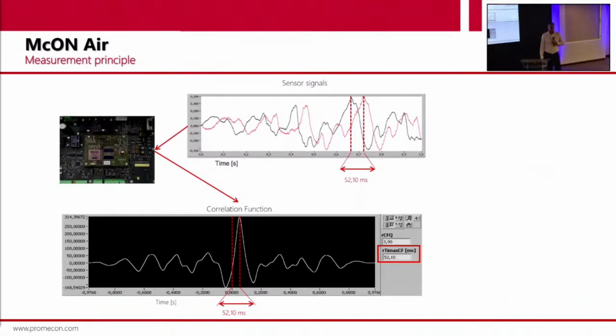Yeah, very simple. We've applied this to thousands of process gas pipes with temperatures from 100 degrees Celsius up to 1,000 degrees Celsius. We also have an optical version of this, which can go up to 2,000 degrees Celsius. So if you want to measure, for example, a tertiary air duct with 1,200 degrees, it's no problem. You can put this also with an optical sensor, infrared sensor, it's the same.